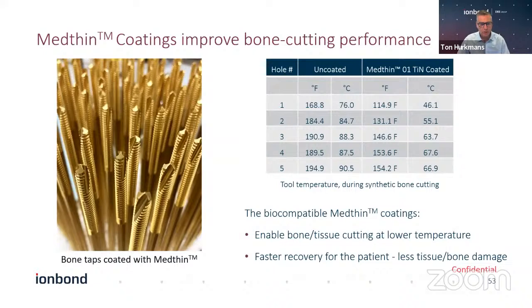Here's another example. Here you see some drills for drilling into bones. There was an experiment done where you see a comparison here, let's say in order of cutting holes in bones, and what is the tip temperature and also then the bone temperature during the surgery. You see here uncoated, in a range of 85 to 90 degrees Celsius developing and killing tissue. And with this coating, titanium nitride in this case on top, it goes to about 65 degrees Celsius. A tremendous advantage in the use of coatings and, let's say, more efficient surgery.